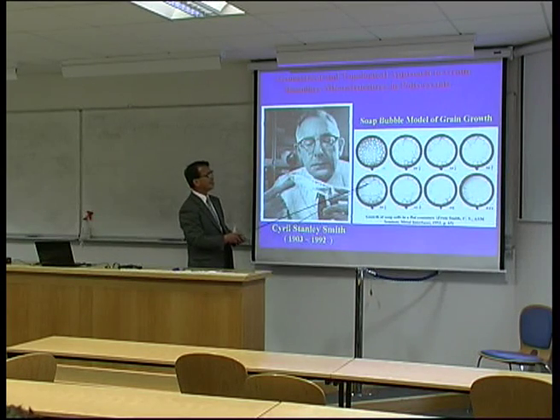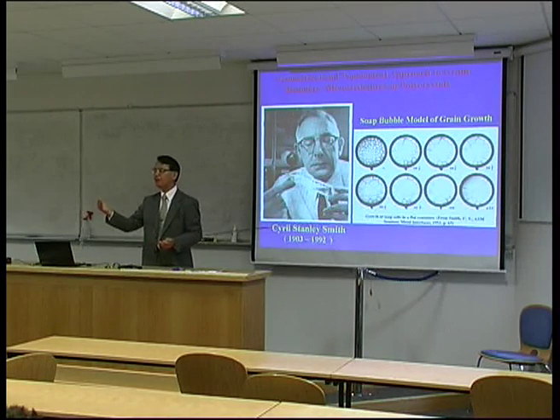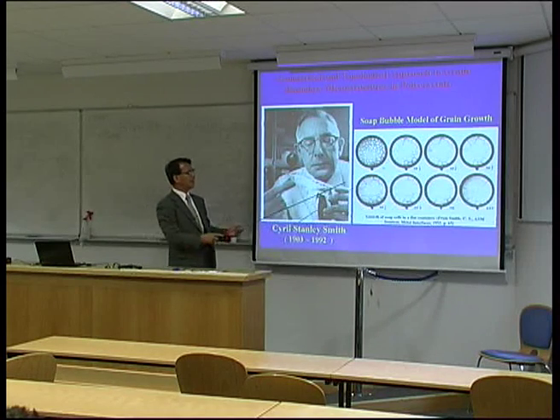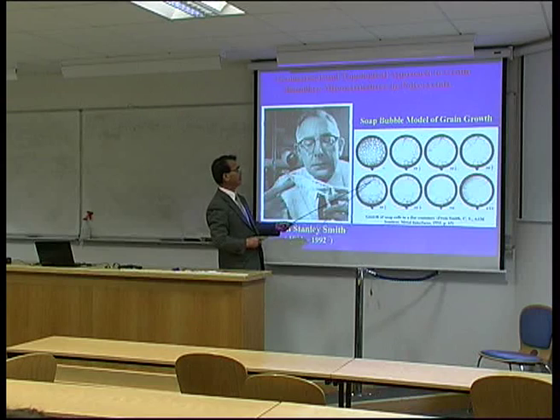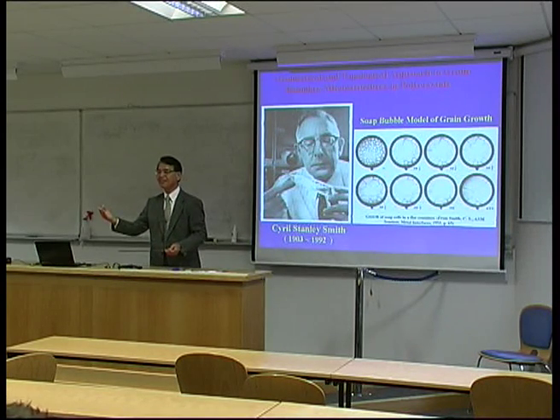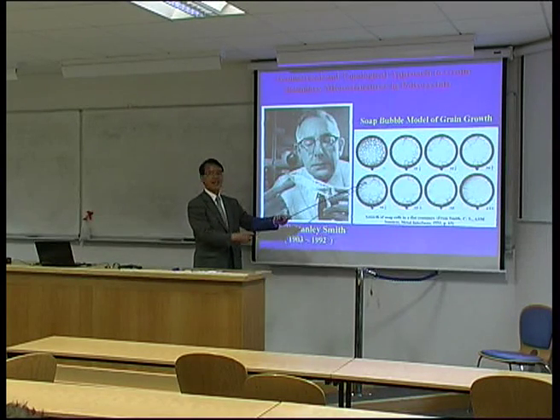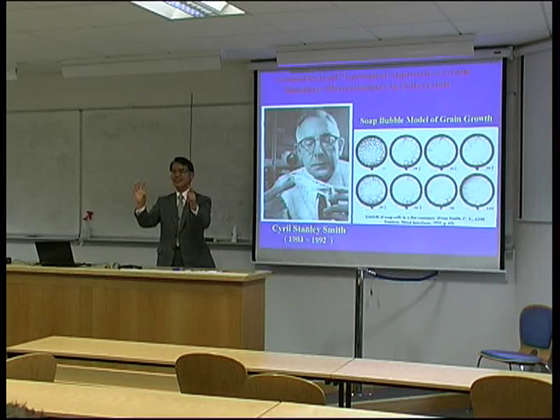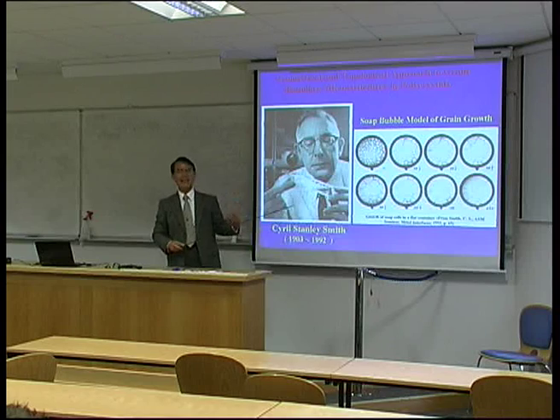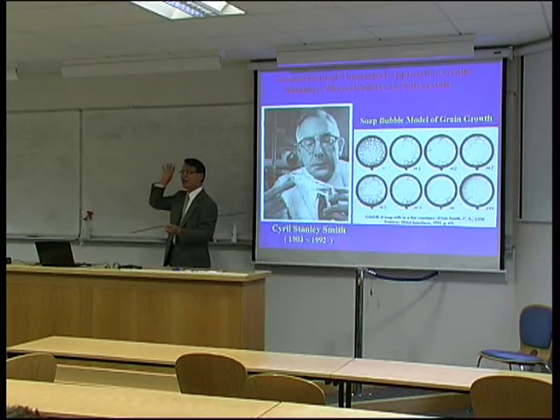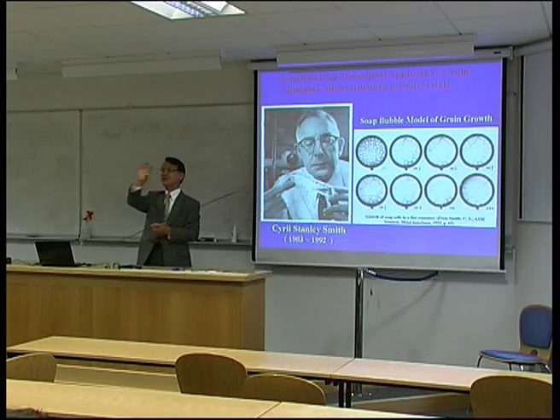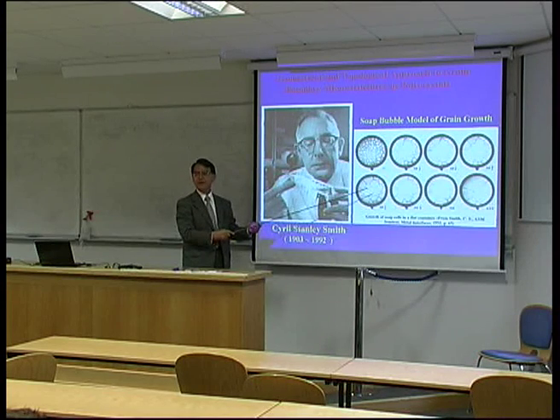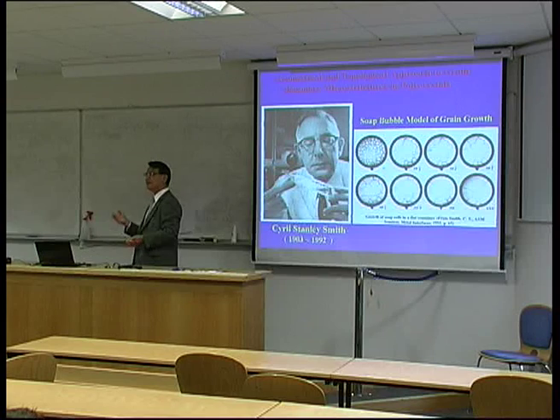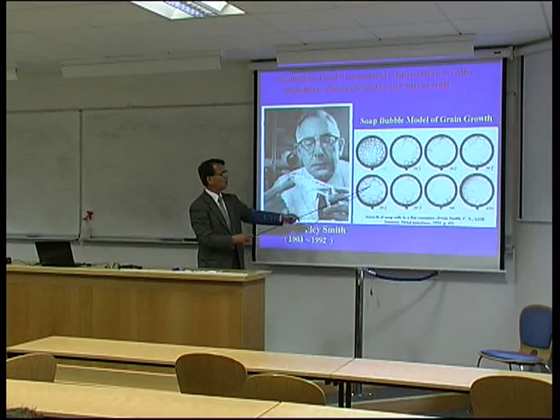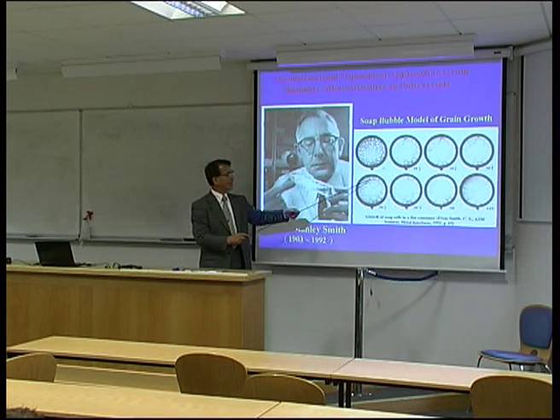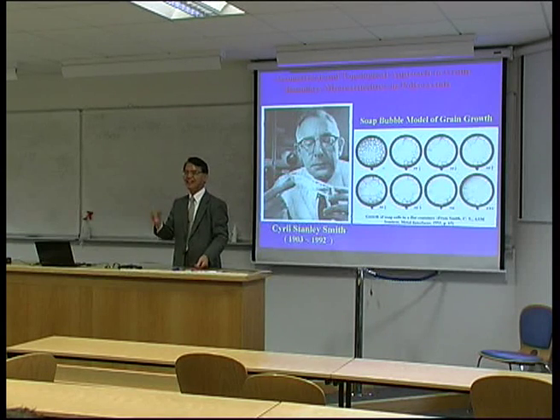But such a grain boundary occurring in a soap bubble is not a real boundary, because in the case of a soap bubble, surface energy remains constant. But in real polycrystal material, each boundary has its own character depending on relative orientation. The boundary is not the same. So there's a big difference. But sometimes it's very easy to use it to give us an imagination of how grains grow. Often we use the soap bubble, and sometimes computer simulation is made, but you should be careful. What is important is that in real crystalline material, each individual boundary has its own boundary energy, not like a soap bubble.